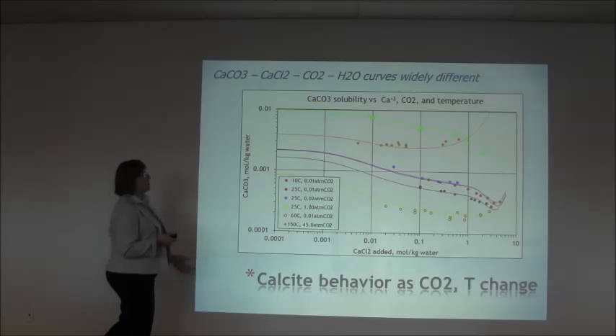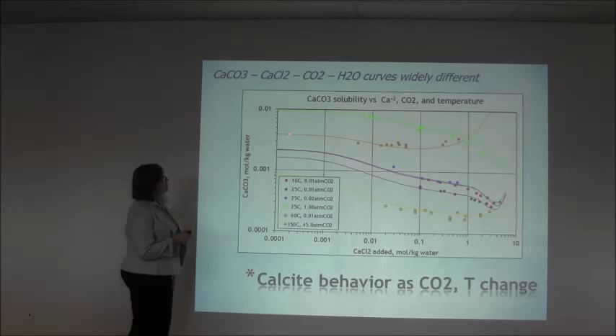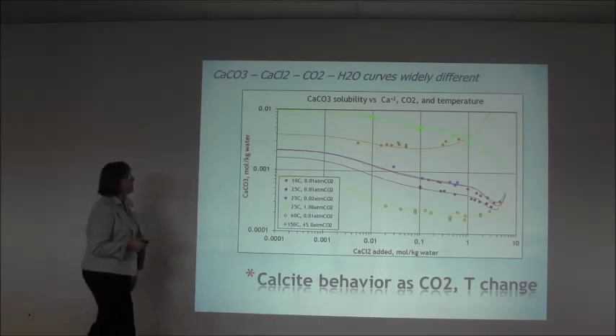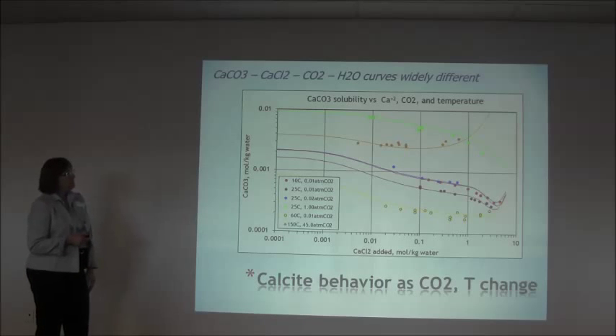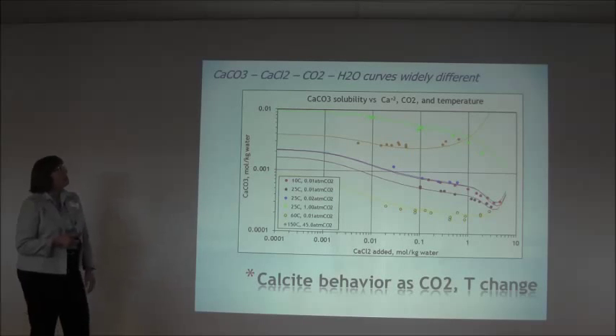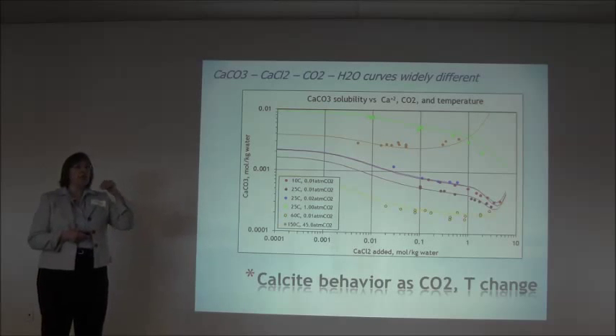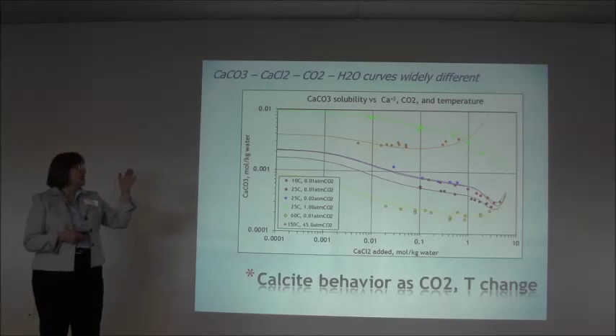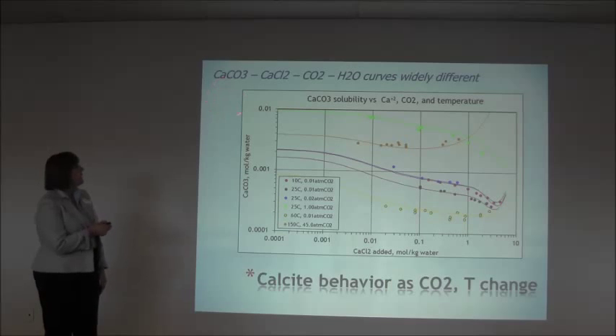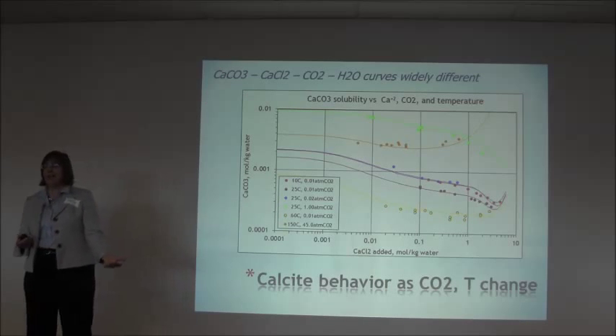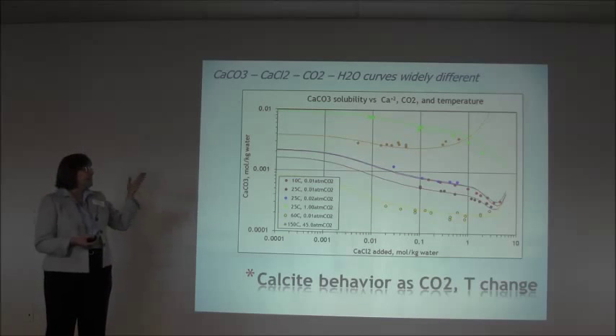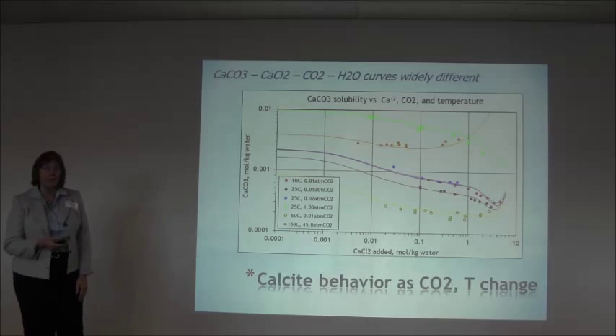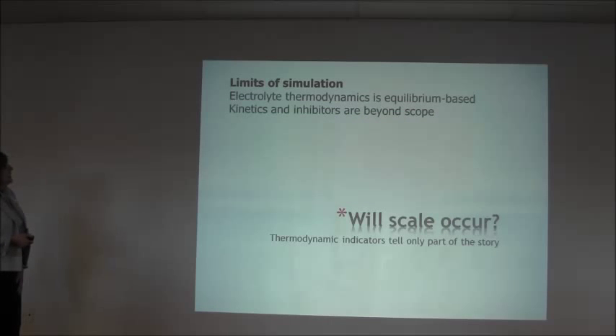What's important about this slide and why you want to talk about it is the difference in behavior. Look at the slope of the green versus the slope of the gold. The gold is a higher concentration with more CO2. But this is not easy to predict. So methods that are less robust, just on a system of, you could say, but I only have carbonate, I only have calcite as my solid, but really the behavior is so poorly behaved for mathematics that it's hard to predict this in a less robust model. So that's kind of the point that we're talking about here.